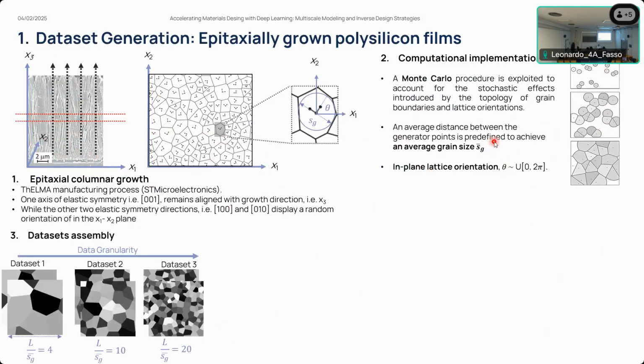With these considerations, we can assemble datasets. For this study case, we assembled 3 different datasets with different granularity levels, characterized by this length scale ratio of L over SG, where L represents the characteristic length of the stochastic volume element, and SG is the average grain size. So we have 3 datasets of increasing level of granularity each.